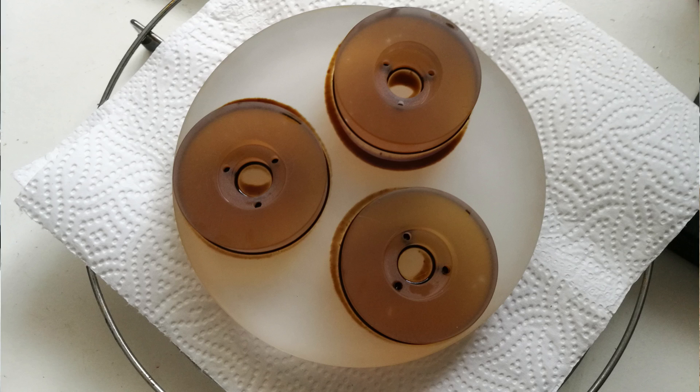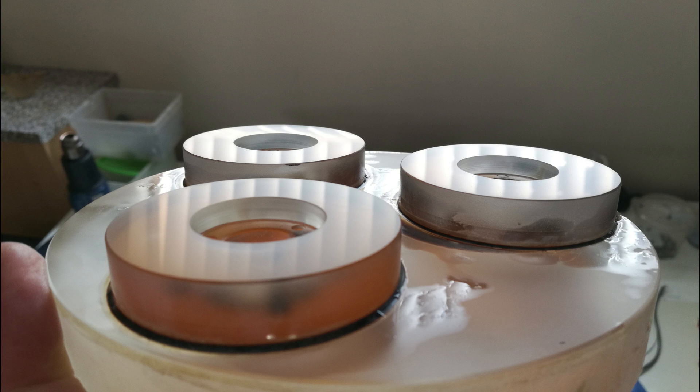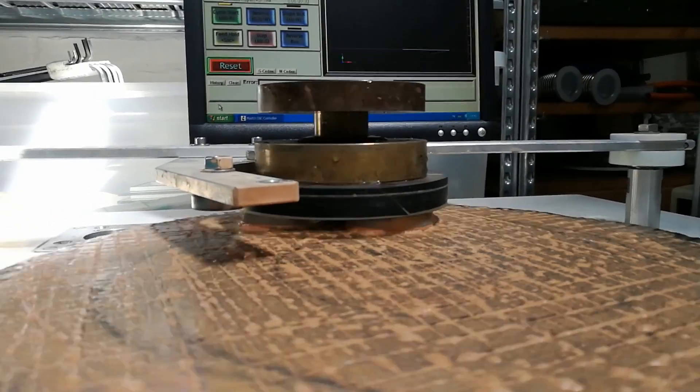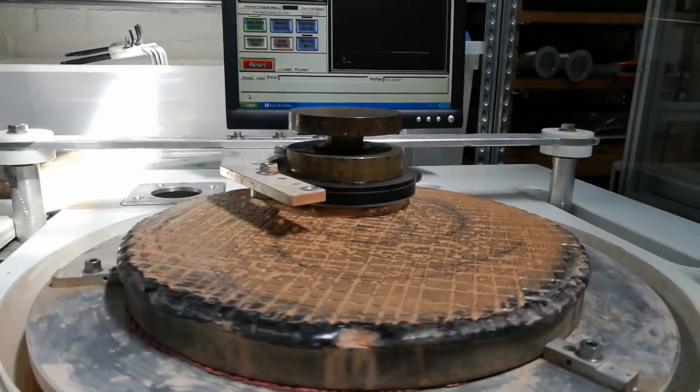So here is a quick example of three parts that needed to be polished flat. They were first mounted on a low expansion glass plate with a thin layer of blocking wax and then ground flat by using a range of silicon carbide powders. The plate with the objects attached was then placed on the machine and the shape of the surface was checked at regular intervals using a test glass.